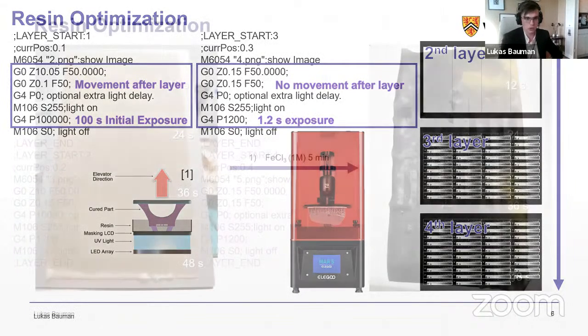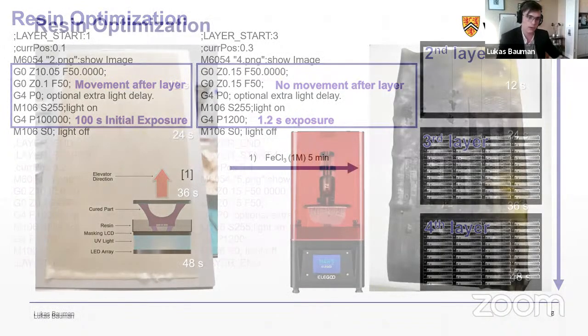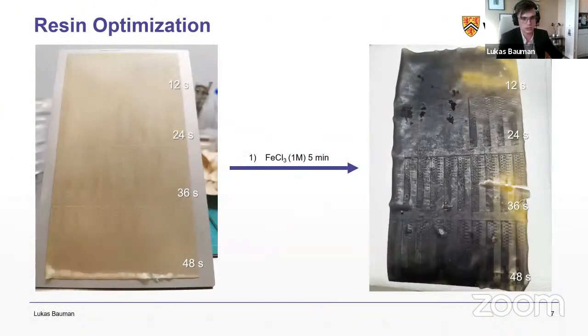So here's an example of one of the exposure tests. Here we can see around 30 seconds is where it starts showing good resolution, and then the best is around 40 seconds, so in the second, third, and fourth rows. Then what we also did was brush this with ferric chloride just to start polymerizing the tannic acid present in the sample and getting that to polymerize on the CNC, so you have a bit more contrast to see what these actual scales look like that you can read for the resolution.